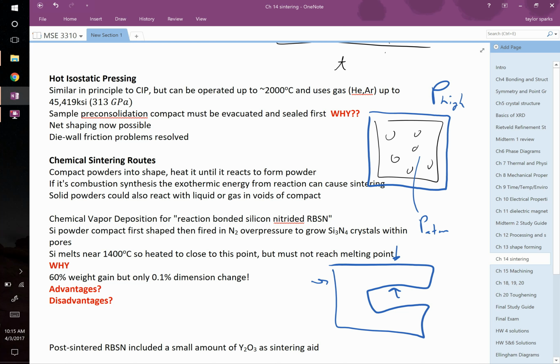If it's combustion synthesis, the exothermic nature of the reaction itself causes sintering, right? As it starts to sinter, that gives off a lot of heat, and that self-propagates the reaction. That was popular for a while. But the solid powders that this compact is made of can also react with liquid or gas that you flow into the chamber, right?